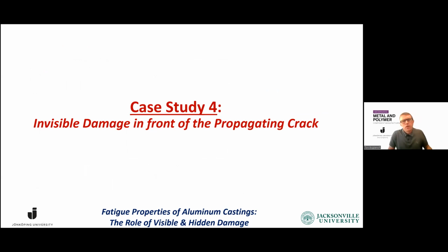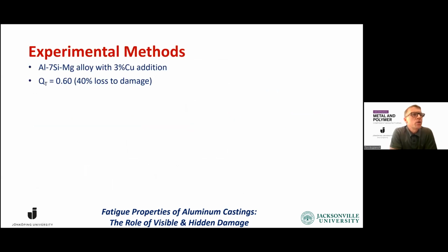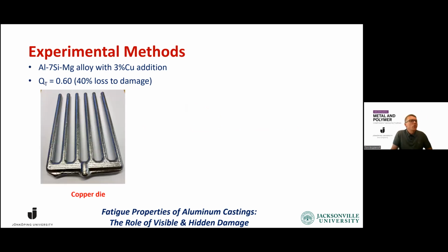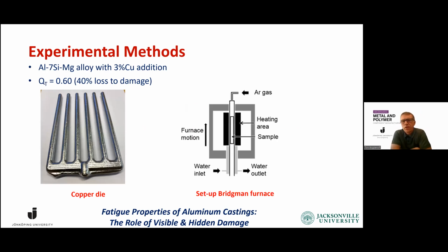Yes. Now we will look a little bit at another experiment that we conducted with aluminium 7 silicon alloy with 3% copper. When we looked at the mechanical properties, we actually reached a quality index of 0.6 with only 40% loss in damage in this material. We cast fingers and then we remelted the material in a Bridgman setup in a furnace where we can control the properties and produce material with low amount of defects.